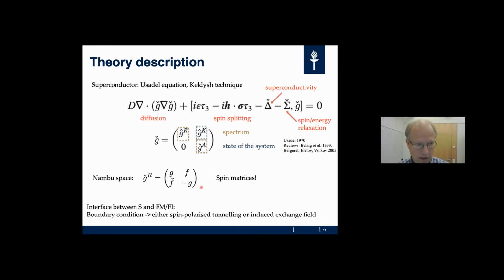In addition to this Usadel equation, which describes the Green's function in the bulk, we also need a boundary condition to describe an interface between a superconductor and a ferromagnet. This boundary condition then describes either spin polarized tunneling or induced exchange field from the ferromagnet.